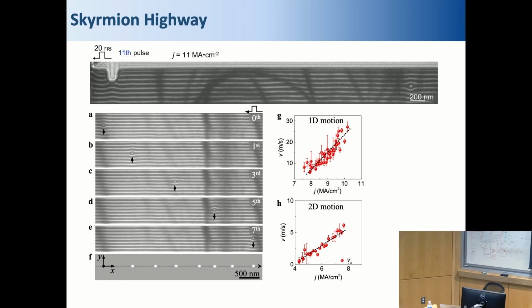What if you have some disorders along the way? Yeah, if there are disorders, then this threshold current will be shifted to a higher value. You need a higher current to drive the motion. But this is the first time we reach the velocity of skyrmion almost close to one kilometer per second. So this is the fastest velocity of skyrmion ever. At large current densities, right? Yeah, and large current density. These are really high. It's decently high.